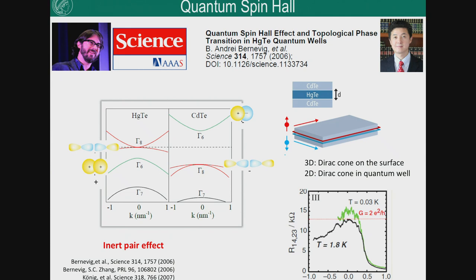At the beginning, some papers thought it's related to spin-orbit coupling, but this is not the case. It's a relativistic effect. If you go to heavy element compounds, every heavy element has the so-called 6s electrons or even 5s electrons contracted due to the relativistic effect. So the s electrons are so close to the core, so they are contracted, and therefore there is a tendency that the s electrons always come below the p and other conduction electrons. So this is already in the atomic limit.